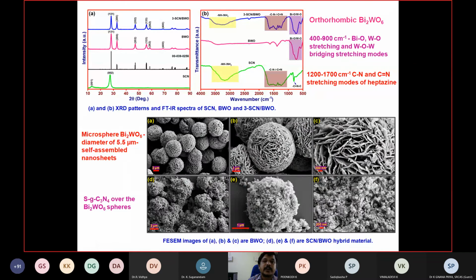Like the previous work, we confirmed that the orthorhombic structure of bismuth tungstate and its crystalline property do not change during the addition of the sulfur-doped graphitic carbon nitride. Also, the FTIR spectrum confirmed the functionalities present in the carbon nitride as well as the bismuth tungstate. Later we did morphological studies. The bare material shows microspheres comprised of several nanosheets of bismuth tungstate. After sonication with the addition of sulfur-doped graphitic carbon nitride, the heterojunction is formed over this microsphere.